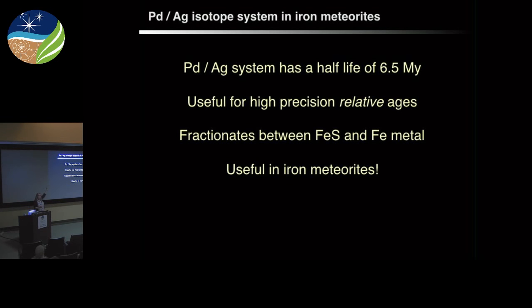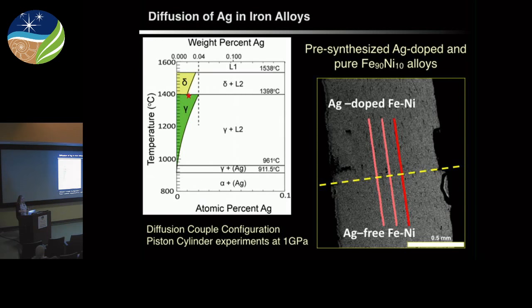This system is really great in iron meteorites because it fractionates between the sulfide and the metal at first. So usually the palladium will go into the metal component as that's solidifying, and the silver will remain in the sulfide. And then that palladium will begin decaying into silver in the metal. And so the silver in the metal is mostly a product of this decay, which is sort of a good context for using isotope methods like this.